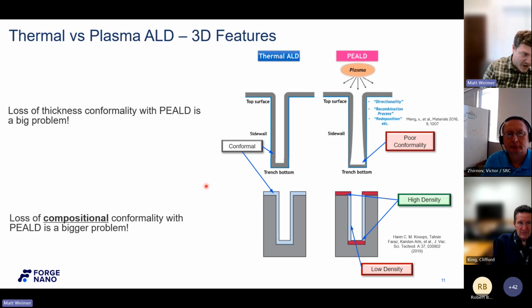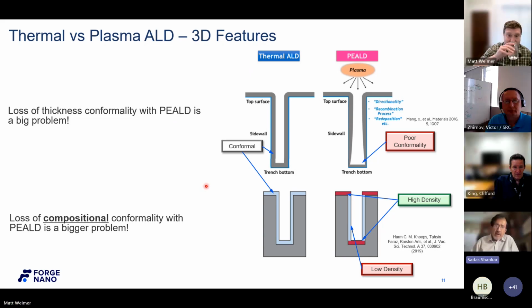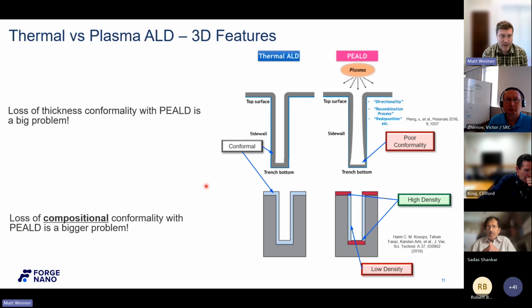Shankar, looks like you have another comment or question there. Yeah, the question I have is, memory typically has a 10:1 aspect ratio or even higher compared to logic. Sure. Do you have a rough idea of how much ALD is used in memory versus logic? Yeah, from my understanding, there's a pseudo ALD process for tungsten metal specifically, that blends the CVD ALD regime where they get a uniform enough deposition to do it. But there's not a lot of places. In logic, it's the gate. Sometimes it's used as a copper diffusion barrier, like tantalum nitride. So yes, a little bit more common there. And I think to this reason. Okay, thank you.